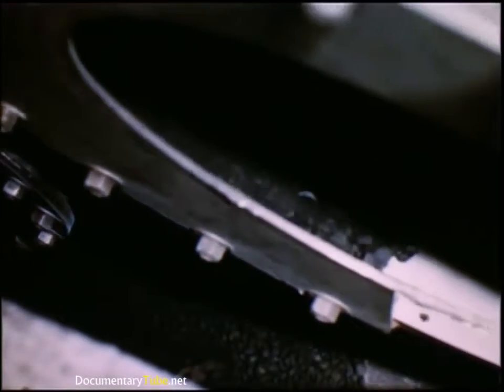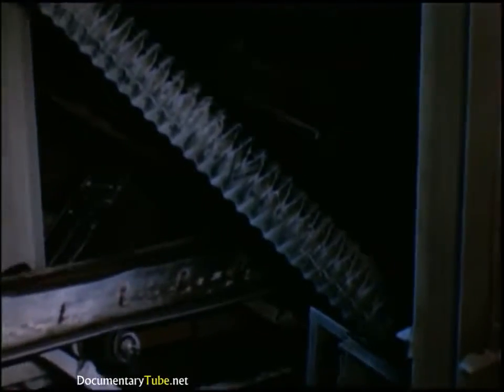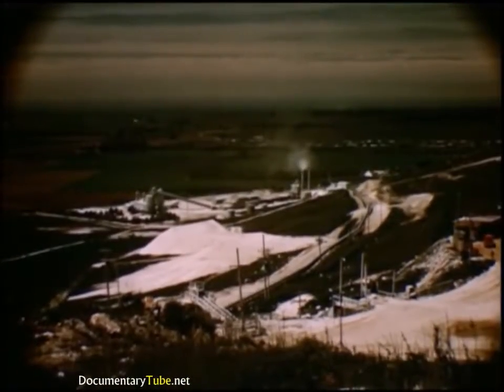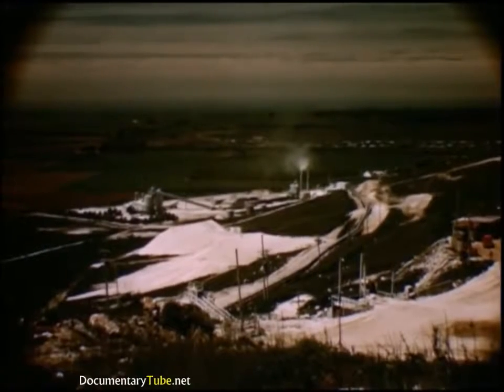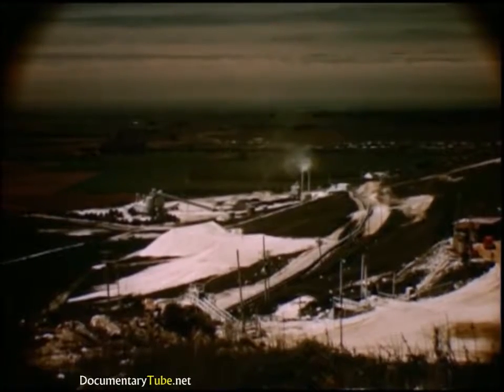Now the simplest of my refractory family, dead-burned dolomite, may be made. Increasing the kiln temperature to 2,900 degrees causes the calcined crystals to shrink to a dense granular mass. This action is aided by adding iron oxide. The iron oxide reacts with the lime and the mass sinters to a dense, hard, very refractory grain. This material is primarily used in repairing furnace bottoms. The processing plant, gradually converting the mountain to a useful material, turns out 16,000 tons of finished chemical products each month.